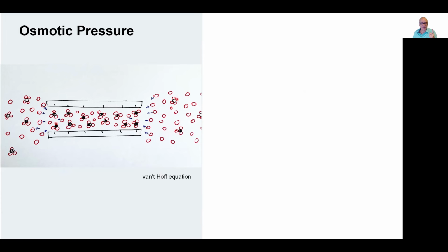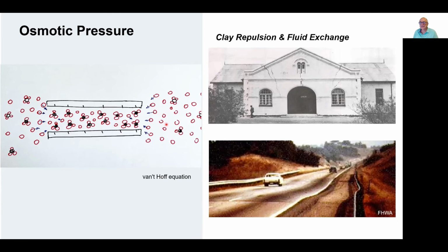The opposite could happen if the pore fluid that goes through has very high ionic concentration, like now salt water, seawater intrusion due to sea level rise. Now this water will have higher ionic concentration. The osmotic pressure will go in the opposite direction, and there will be contraction of the clay, chemoosmosis. And we see these effects throughout all the swelling clays around the country, around the world.